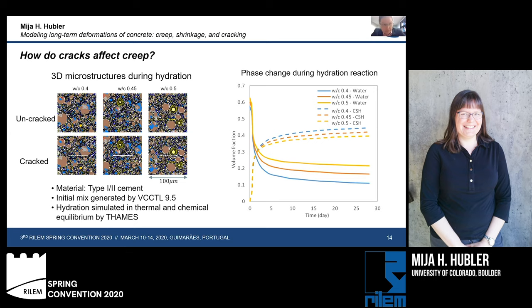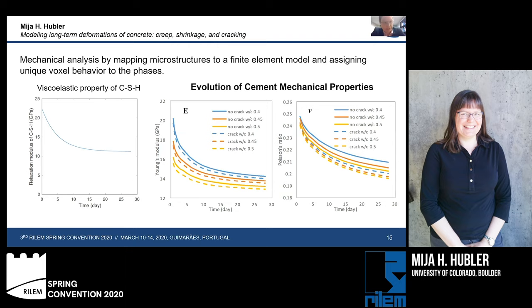Okay, so once we have hydrated our cement virtually, we can now make a mapping of our microstructure to a finite element model and assign unique voxel behavior to each one of our phases. In particular, the viscoelastic property of the calcium silicate hydrate, which underlies the creep behavior of our cement, is assigned. So here we have the relaxation modulus of the calcium silicate hydrate with time.